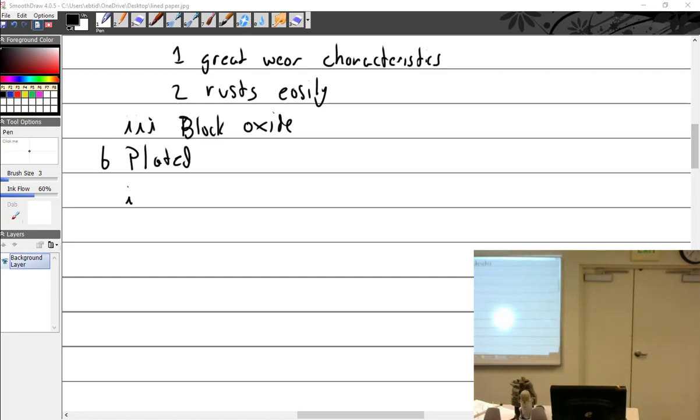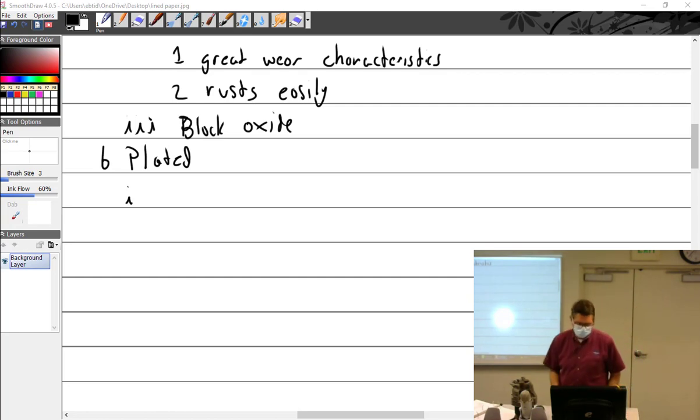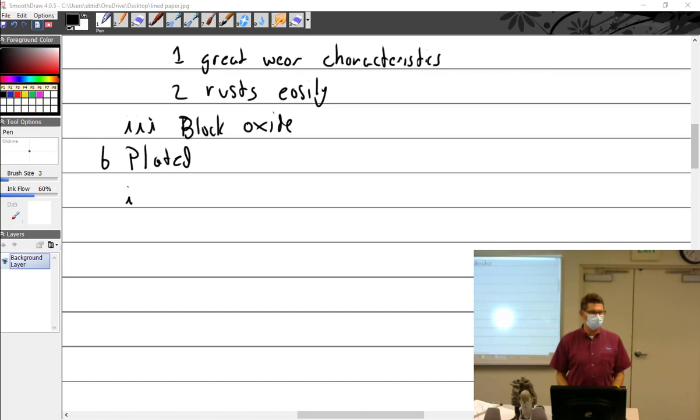The channeling holds the oil so you don't get any oil up there. Over here you can see where it actually wore through the chrome. You have a chrome ring and chrome finish, the two chromes want to eat each other up. They hate each other.